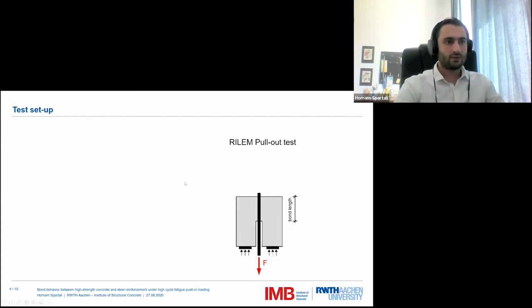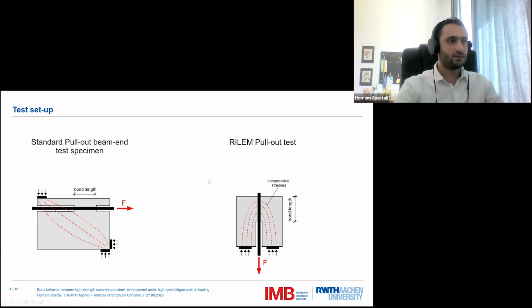Now, the most common test for bond behavior is the RILEM pull-out test. However, it was found that this test overestimates the bond strength because of the compressive stresses that emerge while loading. That's why we used another test setup that is mentioned in the ASTM, called the beam end test, which ensures that these compressive stresses are located outside the bond zone.